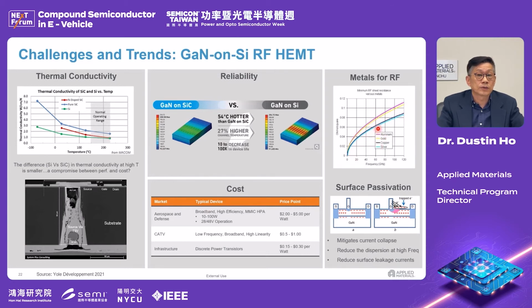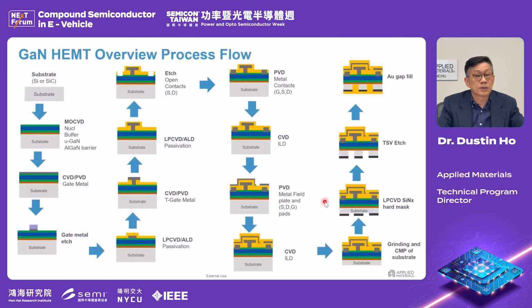And for the metal, like I said, right now most people will use gold, but in theory, for high frequency, copper will be a good candidate to replace gold. Of course, once you use copper, we are familiar with it on the silicon side, but for GaN it's brand new, so you need a lot of work and R&D to improve this. And also the surface passivation, the GaN surface passivation, reducing the roughness will be very important. So still a lot of improvement is needed for us to resolve. And the typical process flow for RF GaN is very similar to GaN power, the GaN HEMT.